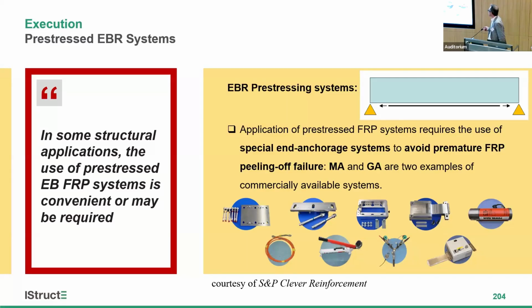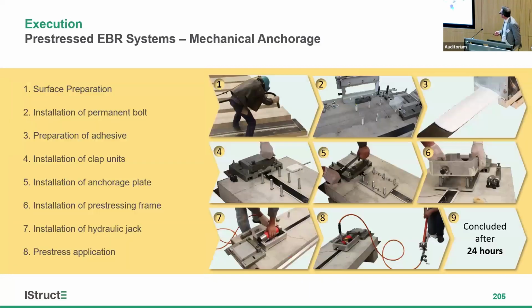The typical examples of commercial systems that you can see in the market are these two that I'm going to detail, the mechanical anchorage and gradient anchorage systems. So basically how they work. For the mechanical anchorage system, we have to start with the surface preparation, which is always crucial. Then you have to install permanent and temporary bolts. You apply the adhesive on the laminate, then install the laminate and fix it in the clamping system. Install the metallic anchorage at the end. This frame is applied to accommodate the cylinder, and then you apply the prestress using the cylinder. This system is concluded 24 hours after the application because we have a certain level of curing of the epoxy.